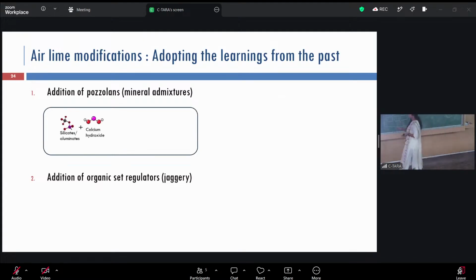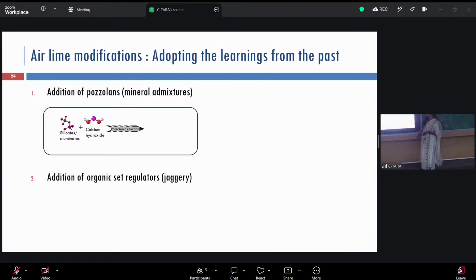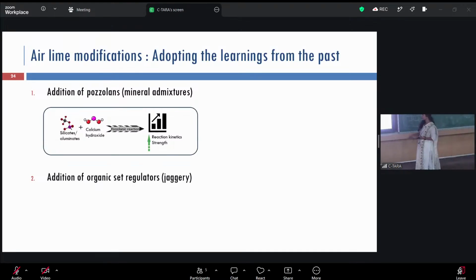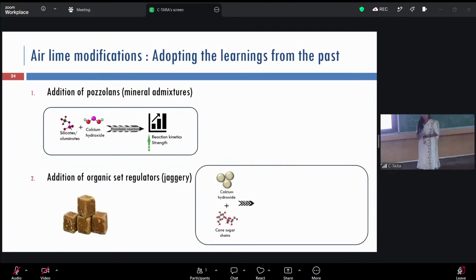So we added pozzolans, which are silicates, aluminates. We added slag there. That will enhance the reaction rate. So you get it quicker than traditional lime, but not compromising any of the other properties of lime that we achieved with jaggery. When you add jaggery, what happens is, in lime, you are having calcium hydroxide molecules.